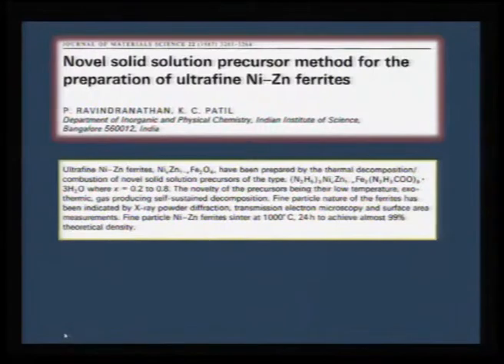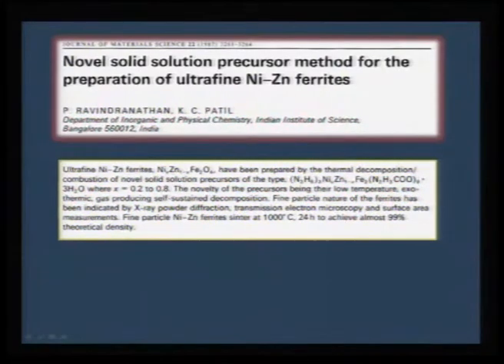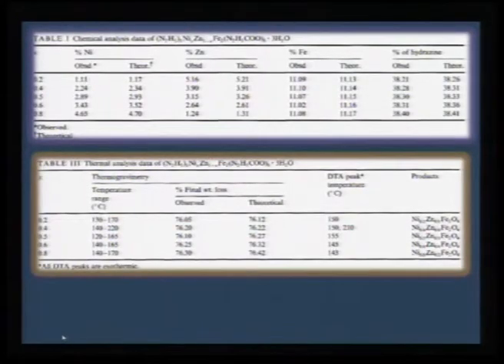If we can make simple spinels, then it is possible for us to make complex spinels also. For example, instead of just zinc ferrite, I can make nickel zinc ferrite, because nickel hydrazine carboxylate, zinc hydrazine carboxylate, and iron hydrazine carboxylate all have the same crystal structure. Therefore, it is possible for me to make a carboxylate precursor as unique as this with this formula. And if I heat this, irrespective of whatever the substitution is, I am going to get the corresponding nickel zinc ferrite, and we can map the composition by studying the element percentage in these precursors. For example, we can analyze quantitatively nickel, zinc and iron present in the precursor, and make sure that we have the right stoichiometry.